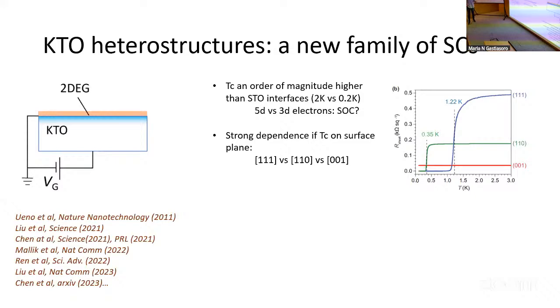I don't know. The other big puzzle is that depending on how they grow these systems, with the crystallographic axis in different directions, TC goes from like 2 Kelvin, 1 Kelvin, to 0. This is also not very typical. And this could give a hint into what the pairing mechanism is, why the system is doing this, and once you understand that, also how it is that I got a factor of 10. That's what would be nice to understand.